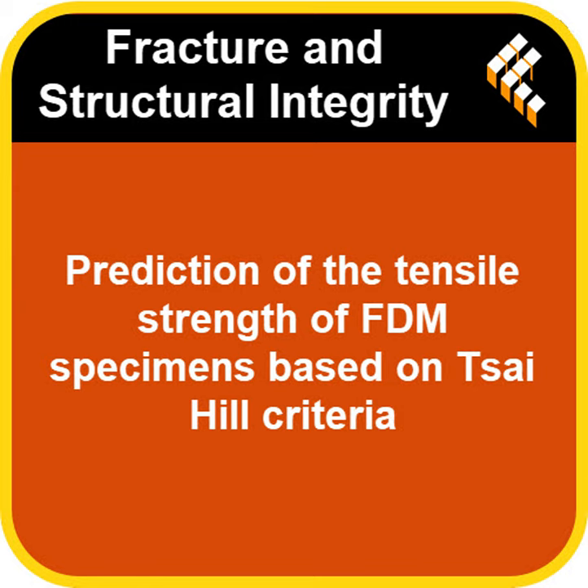The contour, for example, seemed to play an even bigger role in some of the shear tests. So interesting. Okay, let's hear it. What happened when they tried to make the layers slide? All right, so for the 0-degree orientation where the internal print lines were running along the direction of the shear force, the parts without the outer contour performed pretty poorly.